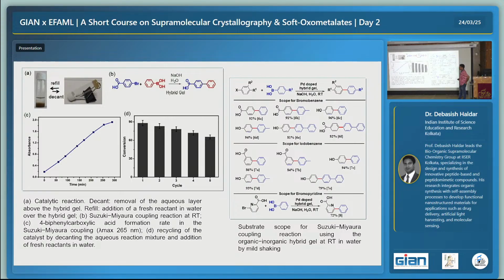And once the compound forms, we just decant the aqueous layer, and we acidify the aqueous layer, we get back the product, and we separate the product by filtration. And again we can top up with the reagent and do the reaction. So we have done this reaction up to 5 cycles with almost 70% yield, which is not bad, because every time we are decanting, there is possibility of some leaching of the palladium nanoparticle from the gel matrix.